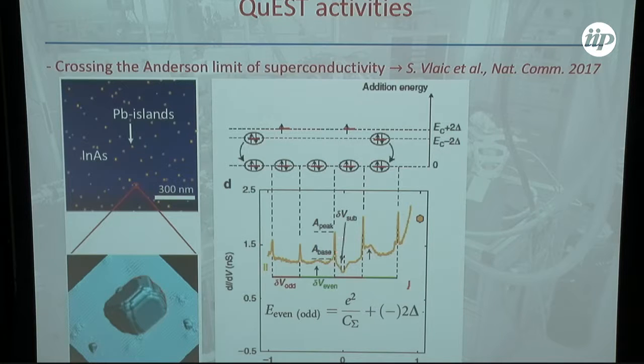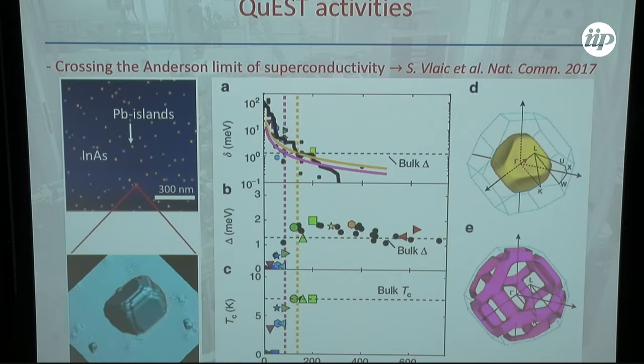So for instance, you can see the distance here is smaller than the distance there, and the distance here is again bigger, and the distance here is again smaller. If you look at the distance, you immediately get information about delta, about the superconductivity inside. We follow this superconductivity, with delta measured directly from this charging parity effect, as a function of the volume of the islands, because nature allows us to have a very wide collection of different sizes. And then you clearly see that this asymmetry, this parity effect, vanishes at about 100 nanometers cubed.